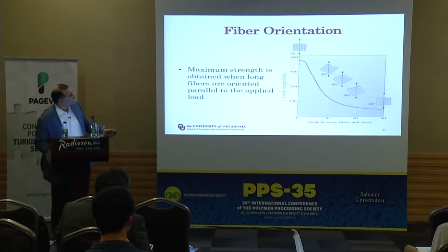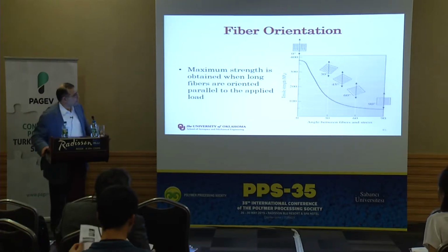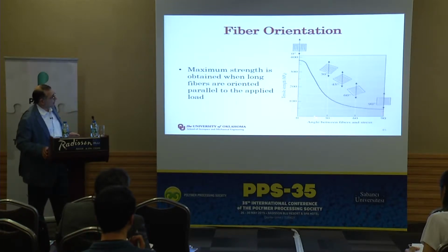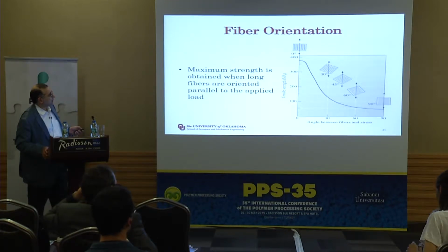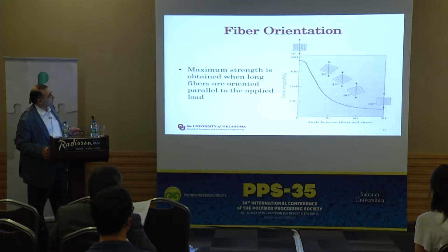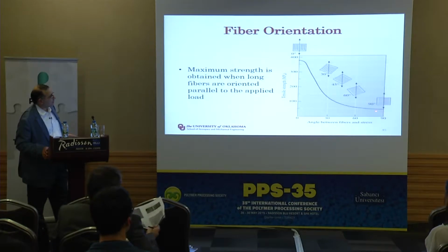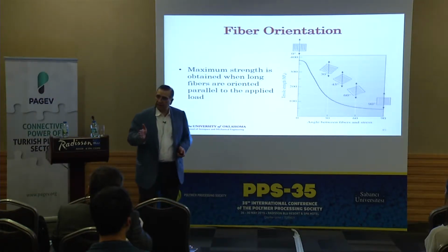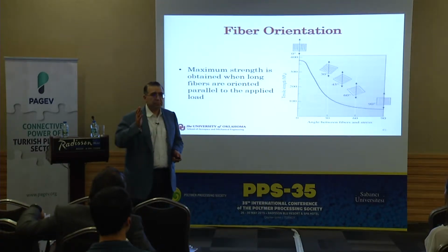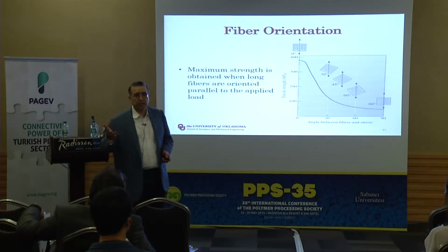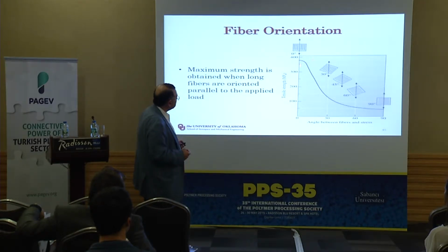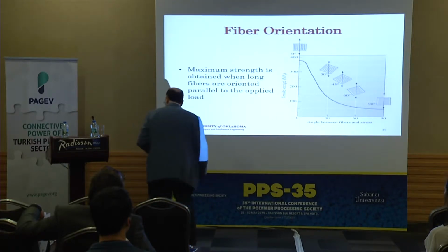Fiber orientation is, of course, very important. We talked about this is the stiffness. I mentioned the equation to determine the stiffness of the longitudinal and the transverse. But this is the strength. For the strength of this composite, if you test it along the fibers, it is almost 400 megapascal. And then it very rapidly goes down. And for the transverse strength, it goes down to 50 megapascal. So you see, if you have a little bit of misalignment, your strength will go down from 380 to below maybe 300. So there's a big drop if you are not perfectly aligned. So you will hardly ever get the maximum benefit from the alignment in the final product you are really using.